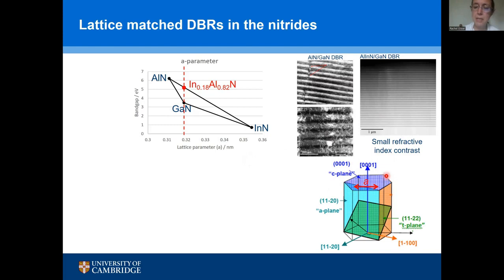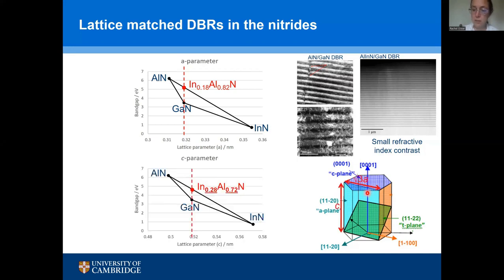I said at the beginning of the talk that gallium nitride has this hexagonal crystal structure, but normally we are growing on this top face of the crystal, if we imagine the crystal as a hexagonal prism, this dark blue face. And we only then have to worry about the atomic spacing that I've got labeled as A here. The problem we had was that we were growing our devices on a different plane, what's called the A plane here. So this rectangular cut through the hexagonal prism, a different face of the crystal structure.